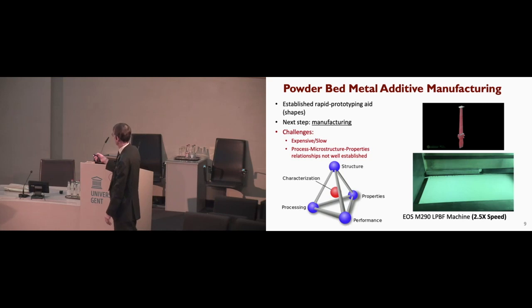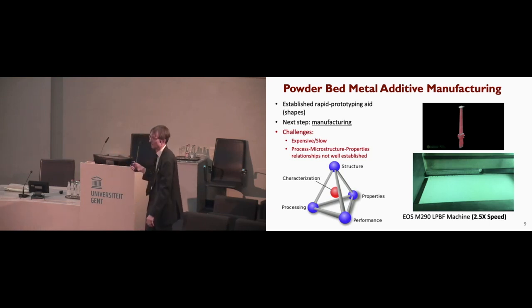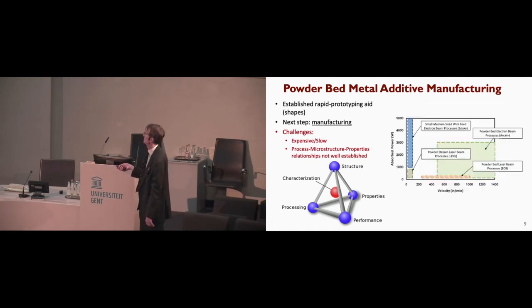Okay, so it was a rapid prototyping approach, particularly I would say with the polymers, although of course people are making real parts with polymers these days as the materials have broadened out. But what happened very quickly with metals was to jump to making real, final parts. And that's part of why metals AM has been such a strong stimulus to the whole area. You can make diagrams, and this kind of diagram of power versus scan speed can be quite helpful. There are differences between wire feed techniques that have very slow scan speeds but can feed a lot of metal in per unit time, versus powder bed systems, where you can write much faster, but because you're spreading in layers, the net deposition rate is a lot slower.